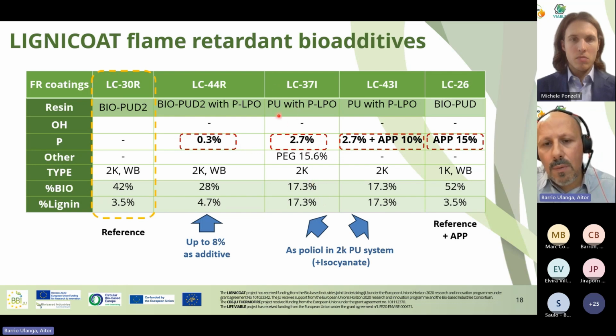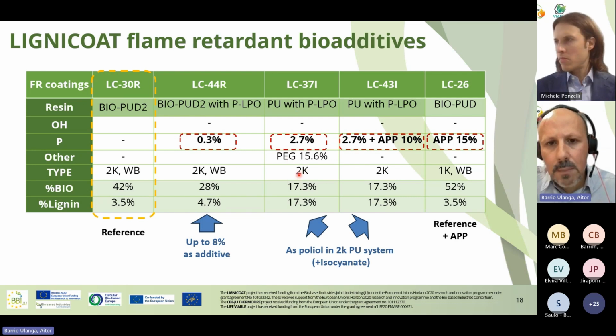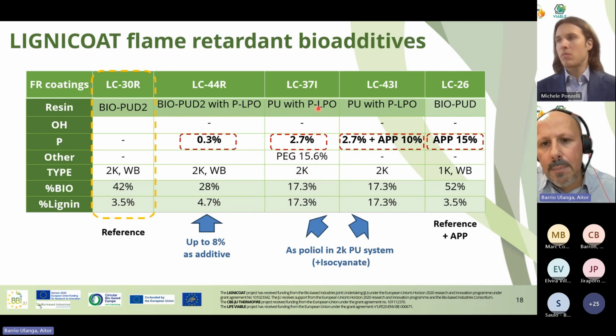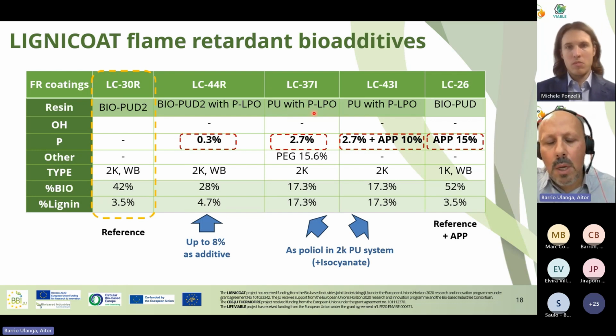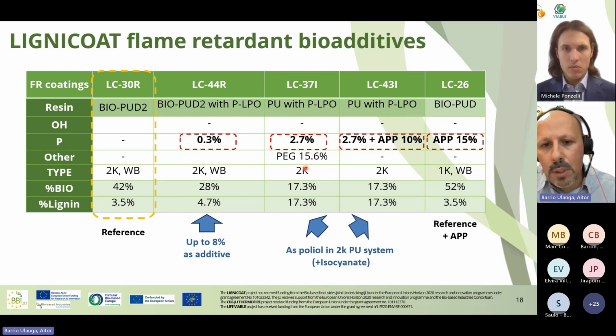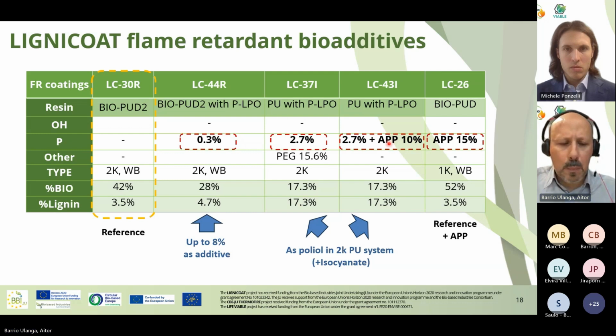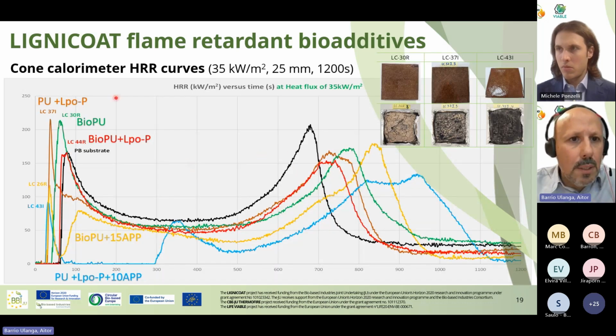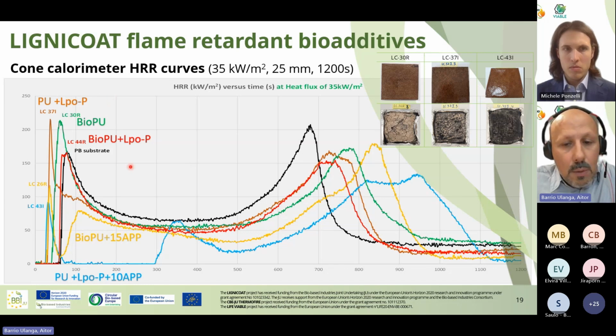We moved to a two-component system using the phosphorylated lignin polyol as the polyol in a typical polyurethane system mixed with isocyanate. And we also prepared a product with 10% of APP. Here you can see the cone calorimeter curves. Claudio is going to explain more later about these characterization techniques, about the cone calorimeter and the other characterization methods. But this is the most used in fire research.